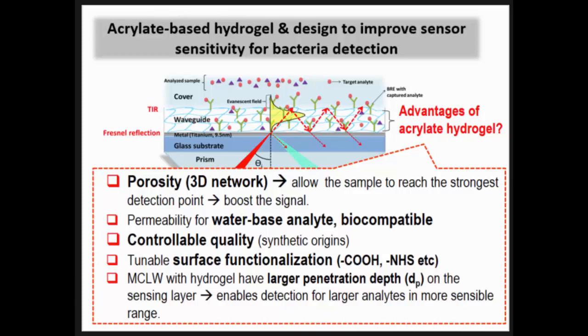The second reason is biocompatibility, and also acrylate-based hydrogel is of synthetic origin, so the quality from one batch to another, we can control properly. In our previous work, we used natural-based hydrogels such as agarose and chitosan, so we couldn't control the quality very well. From one batch to another, we received a different quality. Therefore, we moved to synthetic origins, as we can easily control the surface functionalization that we want to introduce into the hydrogel structure for the immobilization of the protein later.